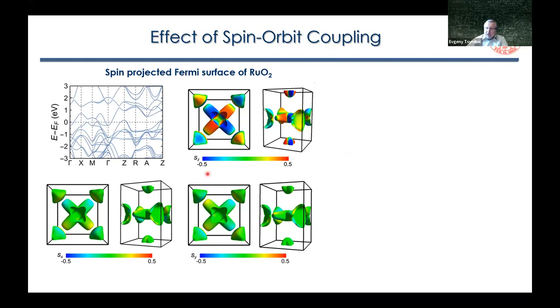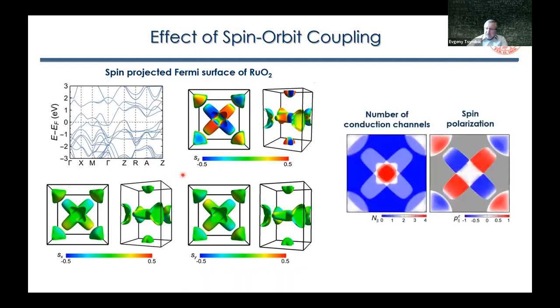And now what I'm showing in color is a projection of the spin to Z, X, and Y directions. So as you can see, the contribution from X and Y directions are tiny. There are some small appearances in regions where there are some crossing of the bands. Moreover, if you look at the number of conduction channels and specifically the spin polarization of these conduction channels, we see a very similar picture as we had before, except again, in some regions where bands are crossing, the spin polarization is somewhat reduced. Otherwise, we have more or less the same distribution.